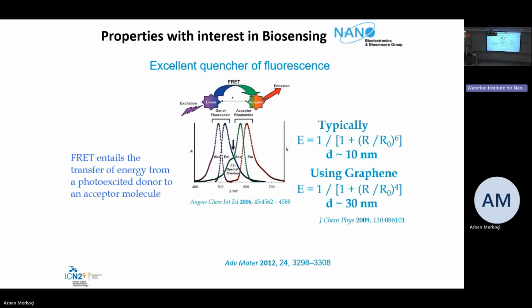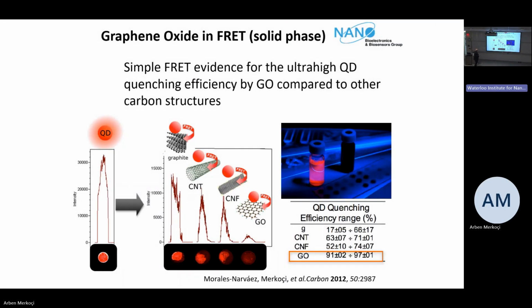So if you have a donor and acceptor for this quenching to occur, the distance is very, very important. Indeed, it is reported to be around 10 nanometers if you work with organic molecules, dyes involved in such kind of measurements. But in graphene, this is reported to be even higher, 30 nanometers. So with this in mind, we compared first the quenching capability, for example, toward the cadmium selenide quantum dot.